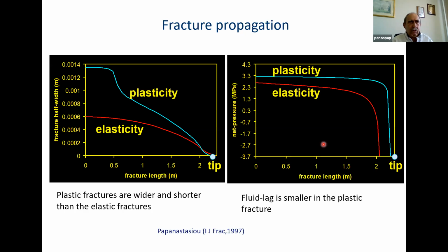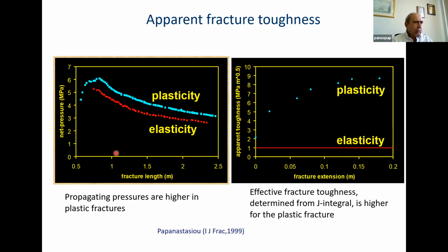And if I go to the pressure profile, we have wider fractures with plasticity. So with plasticity, the fluid front reaches closest to the tip, and we have all the pressure drop near the tip, as you can see here. And back at the wellbore, the pressures are quite close. Next, I will show the net pressure as the fracture propagates, with elasticity and plasticity.